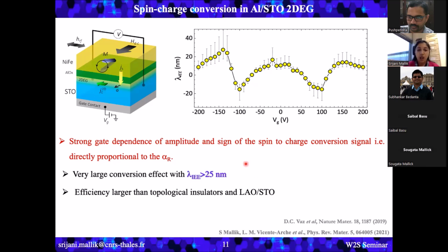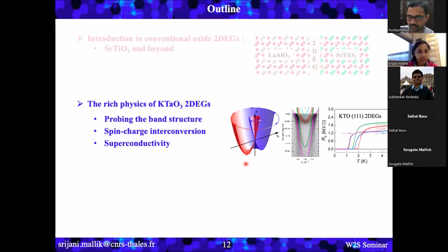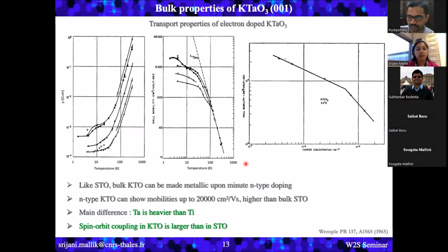So keeping all this information in mind about the conventional STO 2DEGs, I would like to start talking about the main topic of today's talk, the potassium tantalate 2DEGs. Potassium tantalate has many similar properties to STO: bulk KTO can become metallic upon minute electron doping. Also, it shows very high mobilities, like 20,000 centimeter square per volt second. But the main difference between strontium titanate and potassium tantalate is that in strontium titanate we have titanium, whereas in this case we have tantalum. Tantalum is heavier than titanium, and it's expected that the spin orbit coupling in KTO should be larger than in STO.